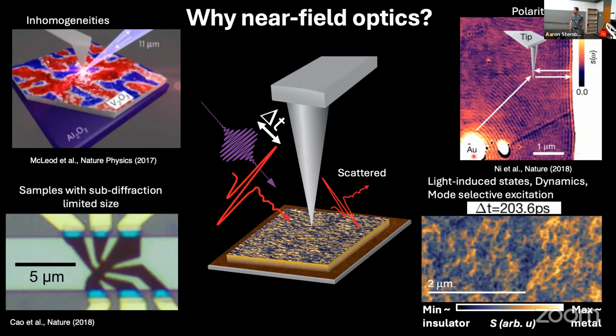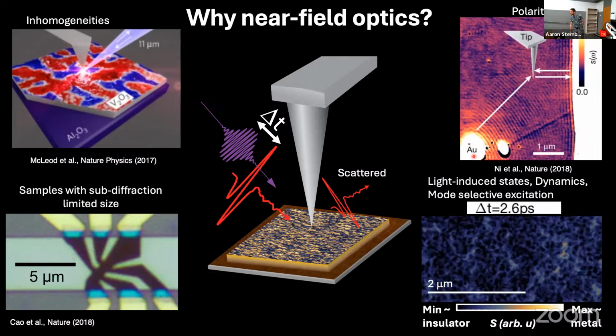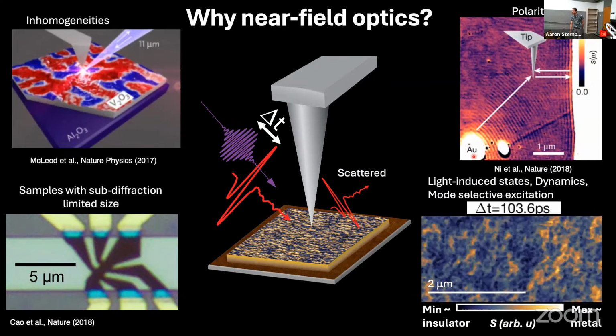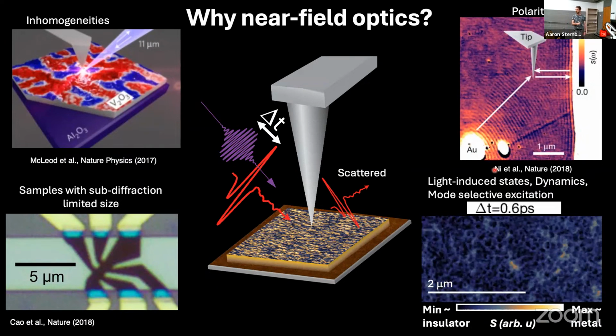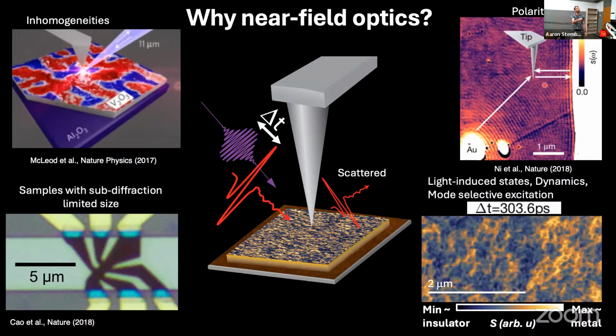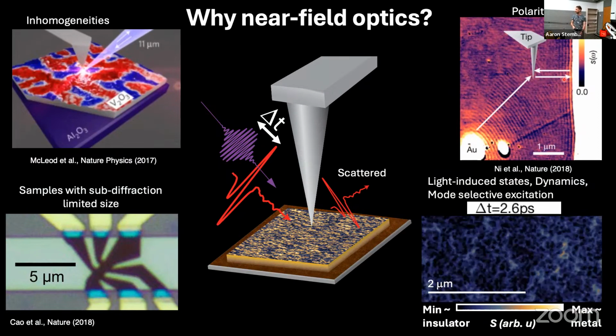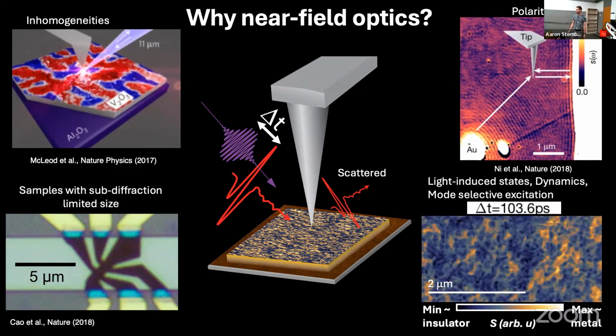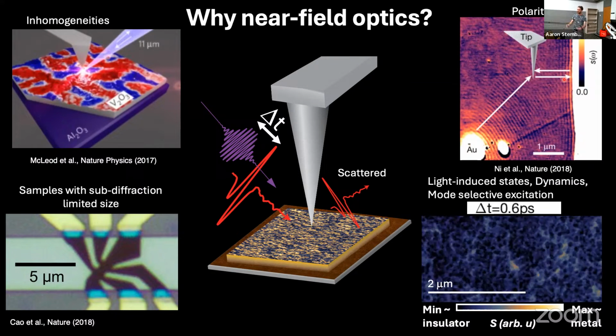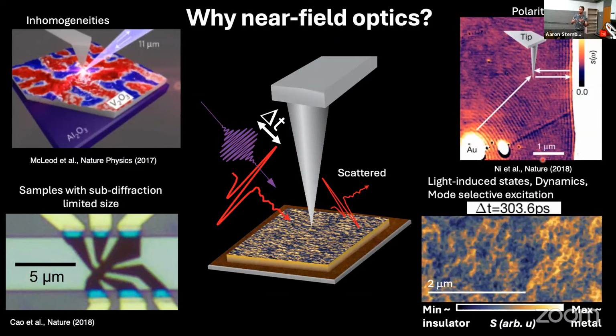In that top right picture, is there a phase trigger that you're using to get the wave? So this is a great question. The phase is essentially set because the wave propagates with a fixed velocity. The phase is set by the distance between the launcher, which is, for example, the tip, and a reflector, which is the gold object. Yes, it creates an interference pattern, and that phase or the standing wave varies from constructive to destructive interference as the distance between the objects changes. You can also measure the near field phase and see essentially how this wave is evolving.